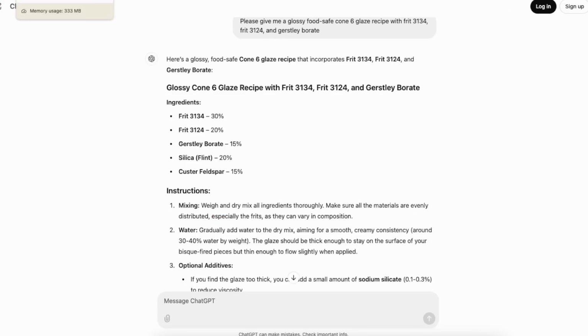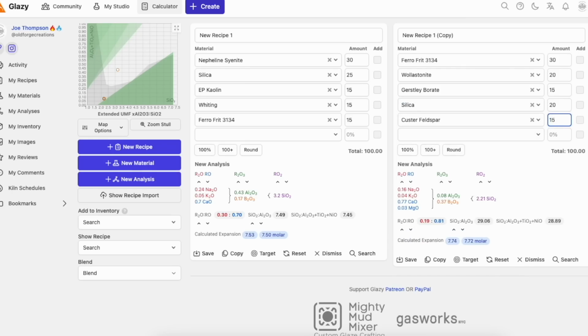So what have we got? So this one is way down here and with something like 2 to 3 times the amount of boron that it would want, even if it had enough alumina in it, which it doesn't because it hasn't included any clay. So there's no alumina source in here, just a trace amount coming from a few different things like the feldspar. So we have, again, an absolute monstrosity of a glaze recipe.